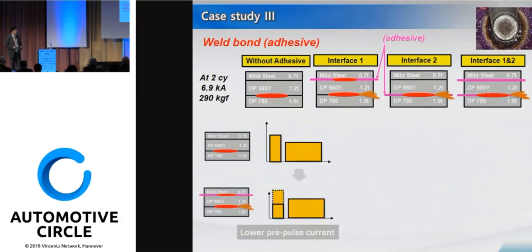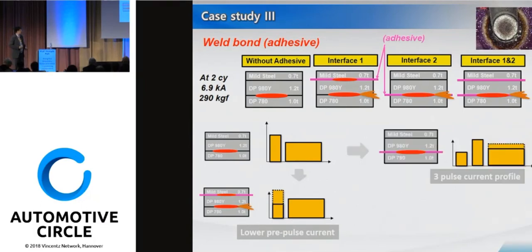Yes, we were able to get the good welds. In the case of adhesive in the interface, since we have a heat generation source from the adhesive, we don't need this high current pulse. So we need to reduce the current here. In this case, we need to move on to the 3-pulse schedule.